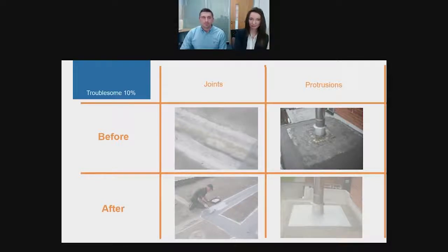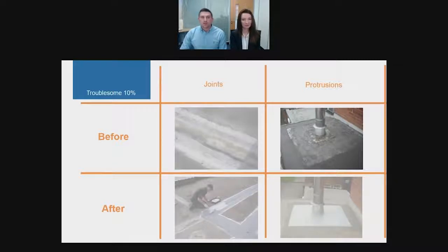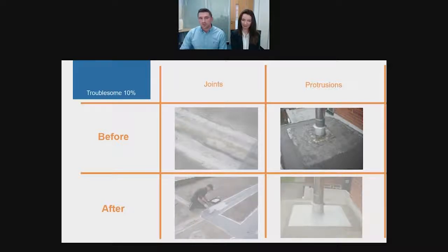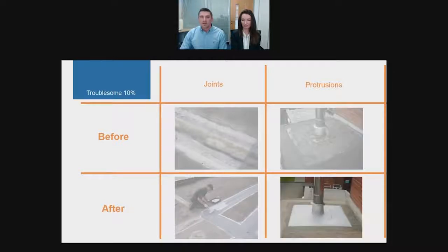Protrusions — anything that penetrates through the roof needs sealing, in this case a pitch pan or exhaust vent. Almost all sealers used will eventually crack due to loss of plasticizer or aging. If it is not stabilized or repaired, the vibration or movement of the penetration can cause the sealant to crack. The sealant used on metal penetration flashings eventually deteriorates with exposure, and may not seal if the flashings have not been correctly cleaned before installation, or if the wrong diameter flashings have been used.